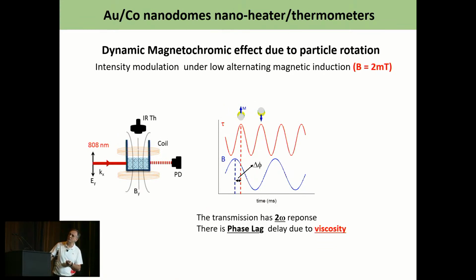And here you see that the optical signal is twice the magnetic field. That is because optically the nanoparticles are the same when they are in this orientation or in this one. So we have a second harmonic response to our magnetic field.